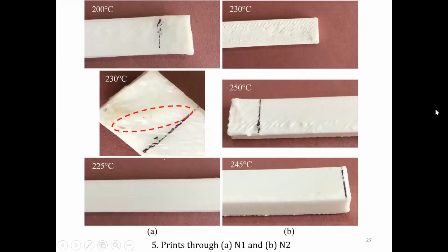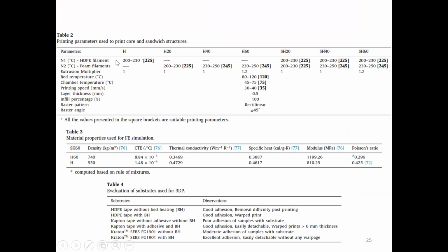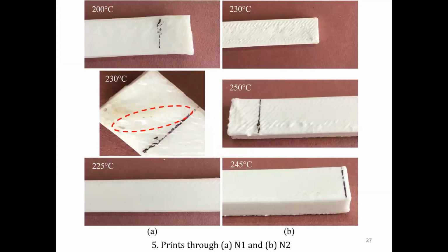I'm going to talk now about the flow of material during printing. In printing core and sandwich structures, the flow of material from the nozzle decides the volume of material to be printed. As we know, two nozzles were exploited. So nozzle temperatures, and one more parameter that comes into the picture here is known as the extrusion multiplier. These two affect the material flow. The temperature of N1 varies from 200 to 230. Now you have seen that in Table 2. I'll just go back to that. Yes, here, 200 to 230. This N1 carries the HDPE filament. So we held it at 200, which results in non-uniform layer deposition. You can see this in Figure A.